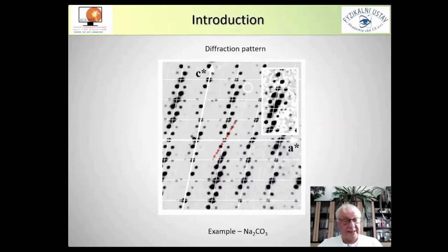The fact that the structure is modulated can be very easily recognized from diffraction pattern. Except of main spots which are making lattice, three-dimensional lattice in three-dimensional space, we can observe additional diffraction spots which are regularly spaced, called satellites, diffraction spots, and they can be indexed also, but with using one additional or more additional diffraction vectors.